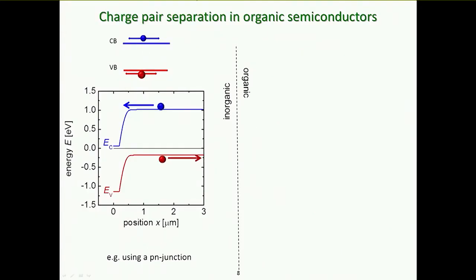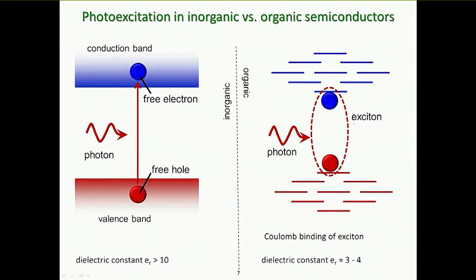The classic picture of a photovoltaic device is something where you can create, by using two electronically different electrodes, a driving force to encourage an excited electron to move in a particular direction, and then give rise to a directionality in the photocurrent. We can't do that in something where the excited states look like this, because a driving force at an electrode some far distance away from this excitonic state will have no impact on what happens to the charges that are bound there.